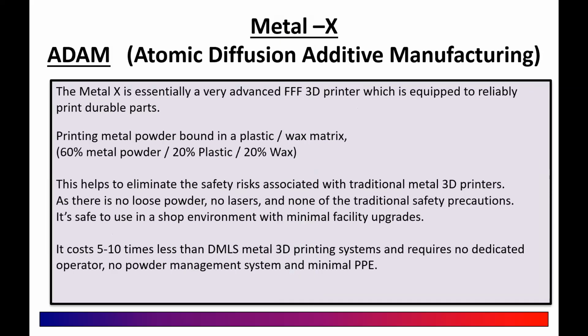So I'm going to talk a little bit just about the Metal X in particular. When it was first released, the name ADAM, Atomic Diffusion Additive Manufacturing, I would like to think was more of a marketing name. The Metal X is essentially an advanced FFF 3D printer. You're taking your material powder that is held within some plastic and wax. As you see, it's about 60% metal powder, 20% plastic and wax. So what we are doing is placing that through a hot head and melting that plastic and wax. We're not actually melting the metal powder. By melting the plastic and wax with the metal powder suspended in it, we can then form the shape of the component that we're looking for.